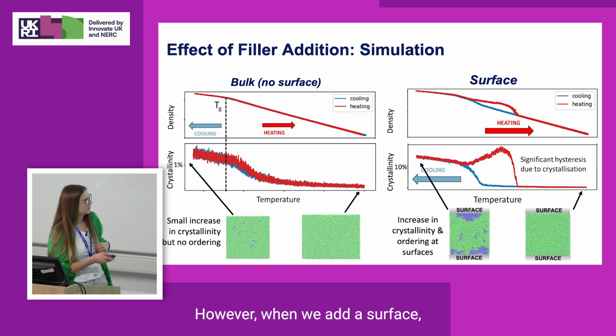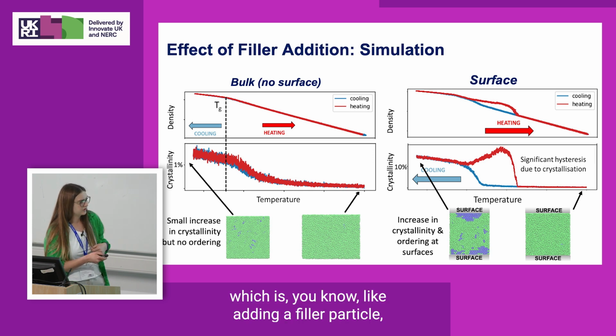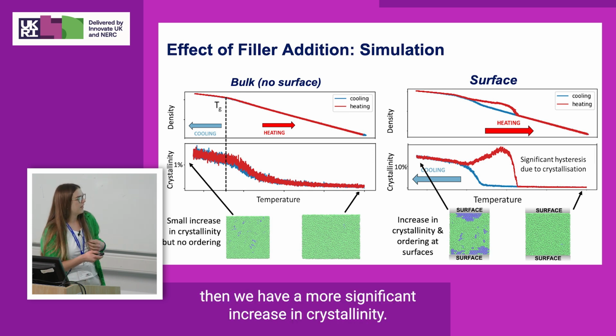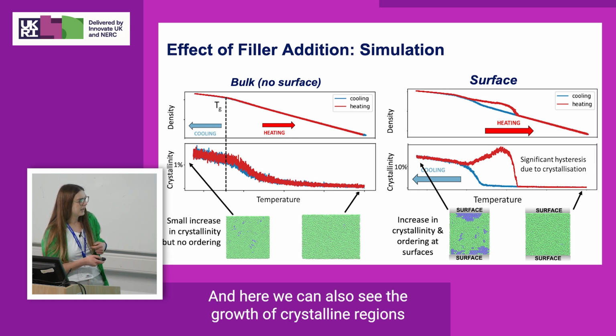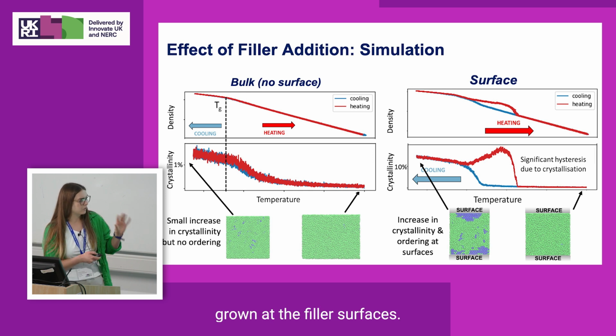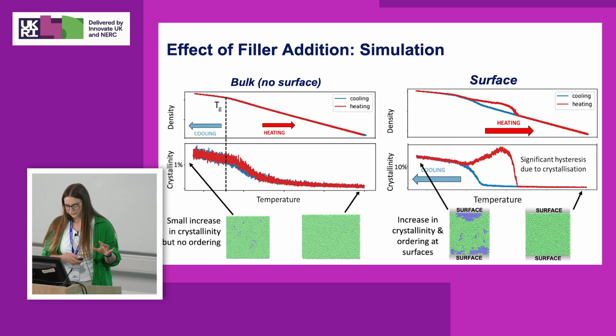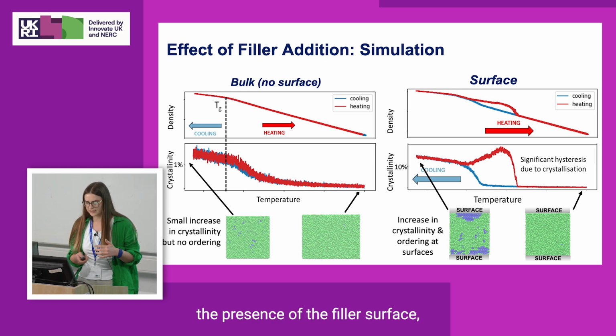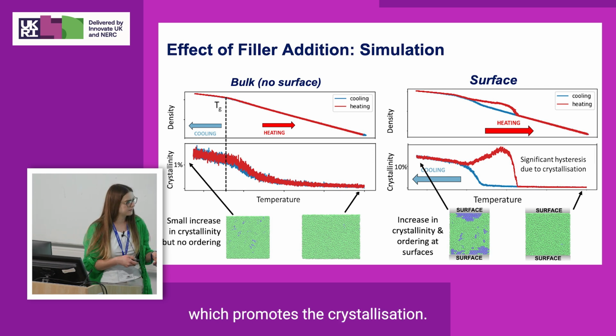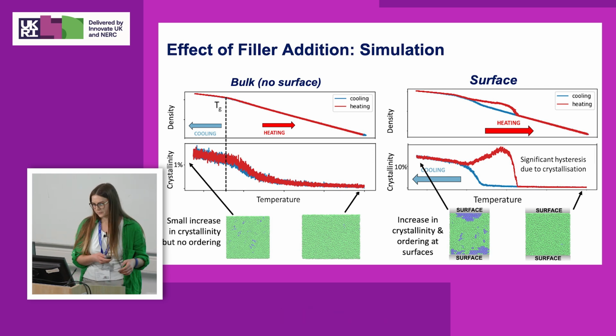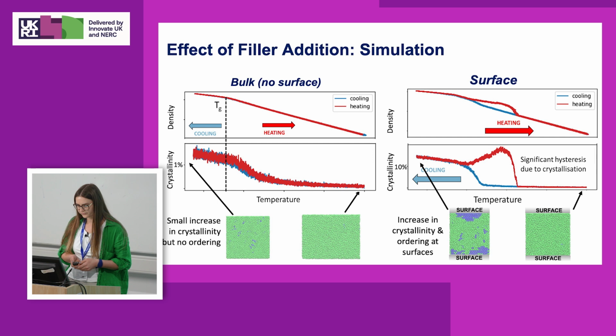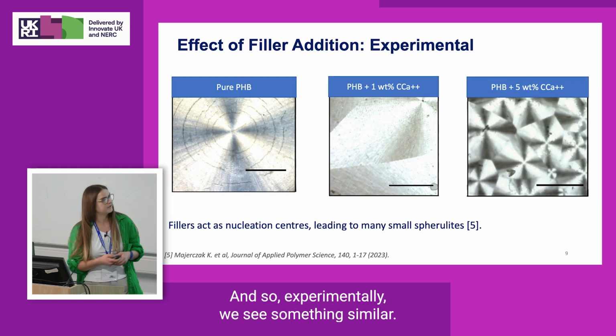However, when we add a surface, which is like adding a filler particle, then we have a more significant increase in crystallinity. And here we can also see the growth of crystalline regions growing at the filler surfaces. And so we know that it's the presence of the filler surface which promotes the crystallization. And so experimentally, we see something similar.